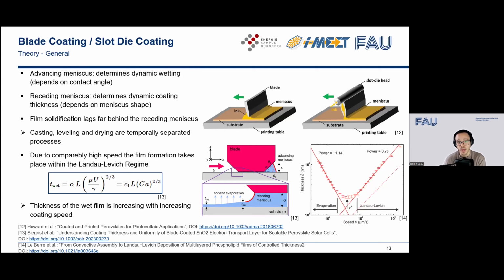In general, we have an advancing meniscus on the front end side of our blade coating that determines the wetting in the end of our ink. And then we have the more important receding meniscus that is on the back end side of our applicator. The shape of this meniscus directly determines the thickness of our wet film and of our dry film in the end, due to the concentration.